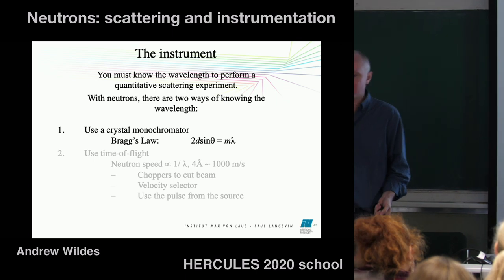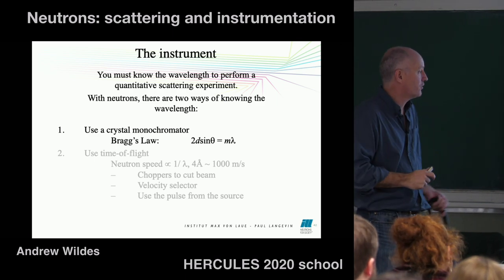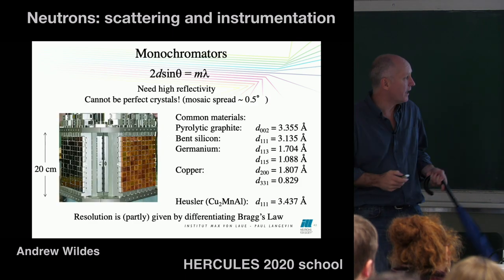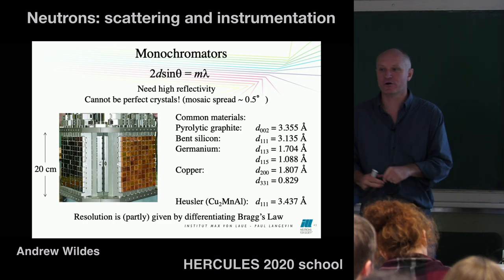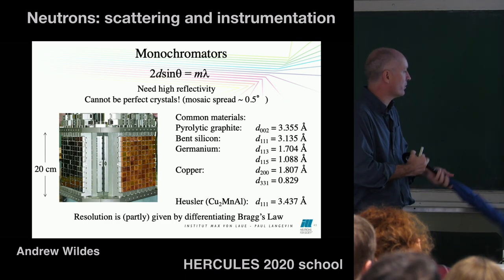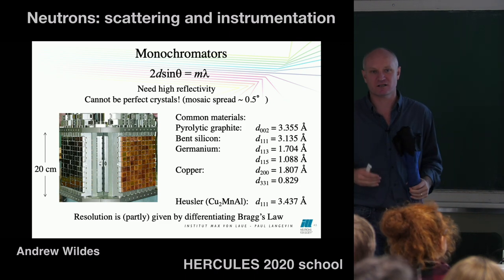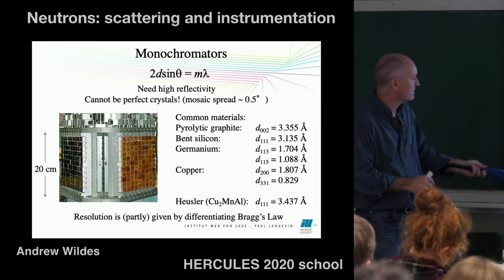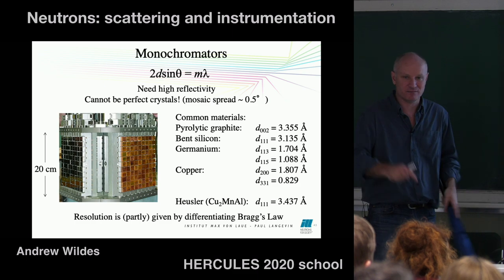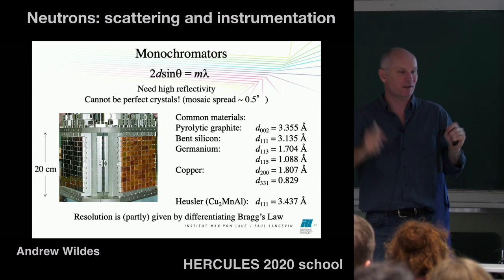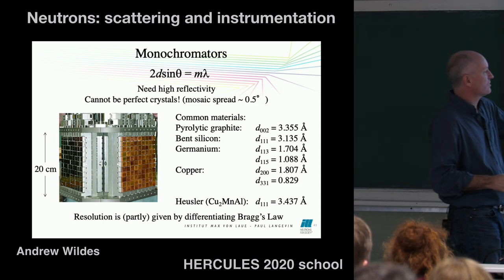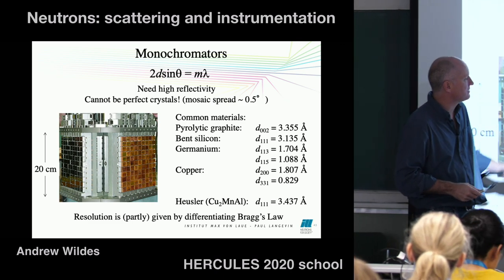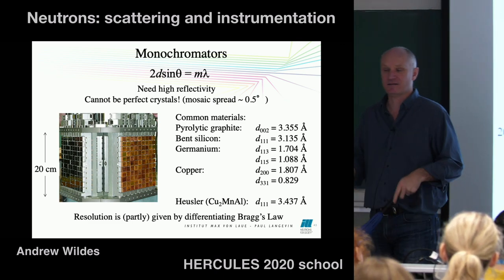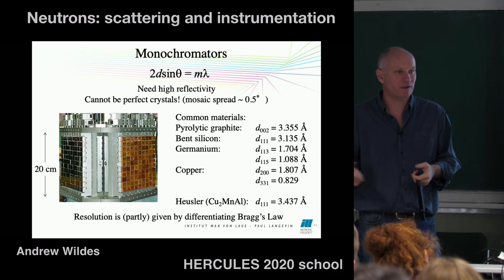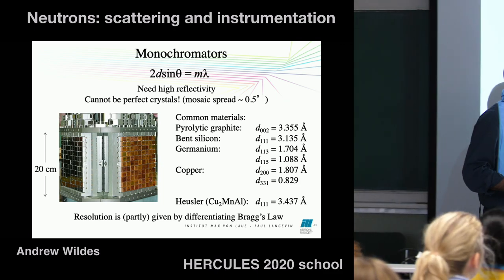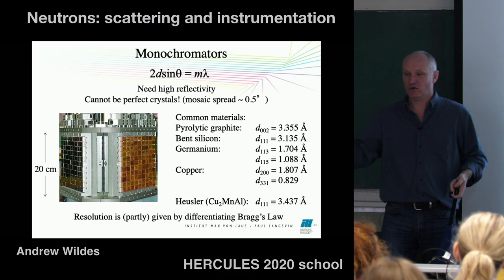Right, so in a little bit more detail, I'll talk a little bit about the crystal monochromators first. This is a picture of a typical monochromator that we might use. This is on an instrument that really needs a lot of neutrons. It's a three-axis spectrometer. So you can see the size of these materials here. They're tens of centimeters large, some of them. Common materials that we use would be things like graphite. That's very nice. It's relatively cheap. It's got a very well-defined d-spacing, and you can get it in quantity.